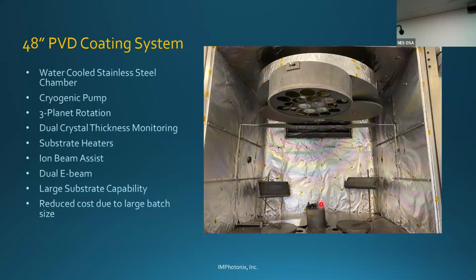Now, with the coating systems, there's one crystal in the center here. Because the parts are rotating and the crystal is stationary, you're not going to get the exact same thickness on the crystal as you get on the parts. So to qualify a chamber, we run a coating with 100% equal what we call tooling factor. Then we take the witness sample and measure it on a spectrometer, reverse engineer through TFCalc what the thickness was, and add that tooling factor correction into the Inficon. Then that's constant with that process. And that's how we use it.